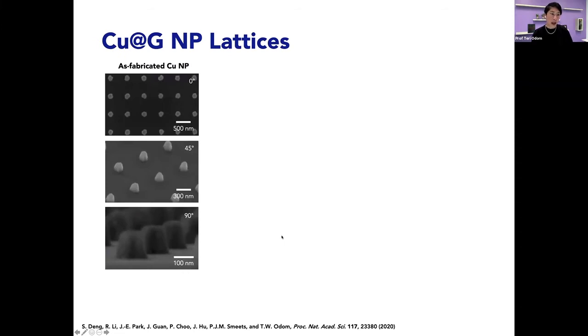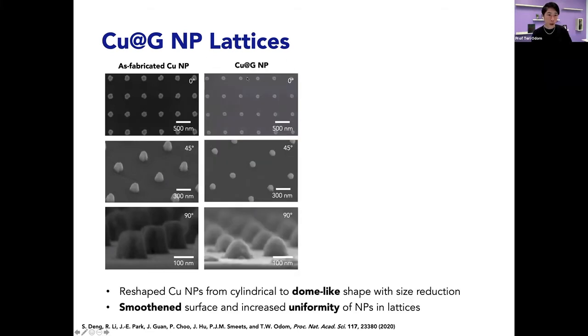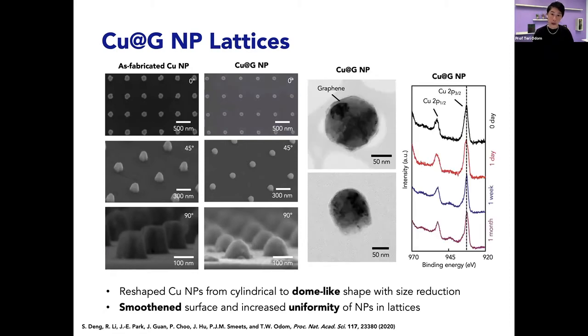So these are what the as-fabricated copper nanoparticles look like. They're not annealed. You can see that there's still rough edges, but the sizes are quite good. After we grow the graphene around the copper, you can see, because of the heating effects, that we have this dome-like structure, but they look good.